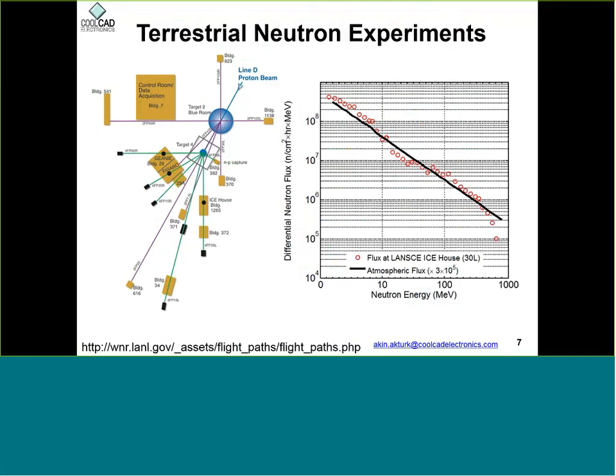It can travel part of this drift layer and can still cause a failure, which is mostly the case for silicon devices. So to perform the test, you can either go to a very high altitude and use many samples and test them over long periods of time, or you can go to the only terrestrial neutron simulator that's available in the US, and that's located at Los Alamos National Lab, at the Los Alamos Neutron Science Center, or LANSCE.